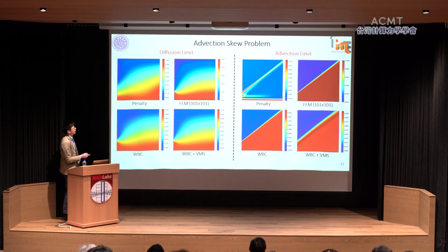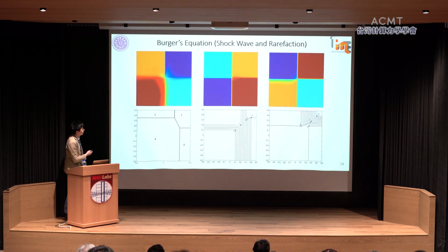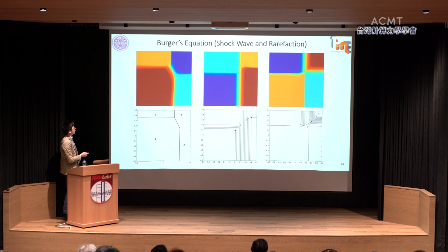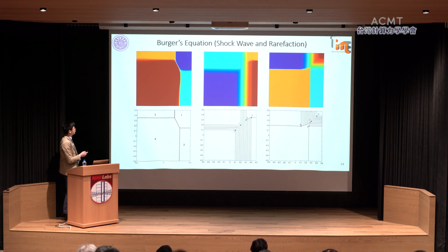Also, here you can see that at the advection limit, the penalty method directly diverges. And my solutions, WBC and WBC plus VMS, are very close to FEM. WBC shows a little bit of overshoot and undershoot behavior that VMS can cure, but from the 2D figure I cannot show that. And this is my recent progress on shock modeling for Burgers' equation. You can see that I apply the method to the nonlinear transient Burgers' equation, and you can see that the shock wave, rarefaction and shock nodes are captured.